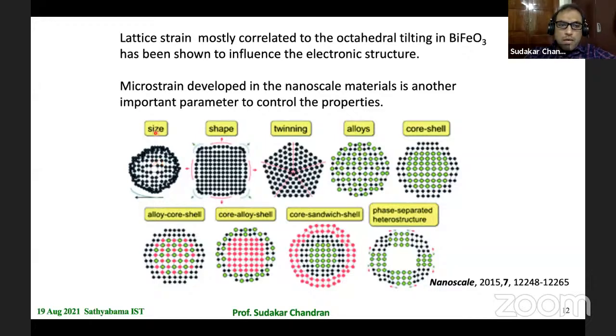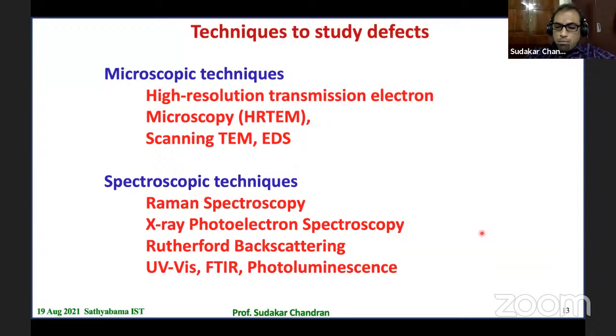And this microstrain can come because of the size or shape effect, and it can also come because of the alloying, or what kind of core shell structure you have, and lots of other things can contribute to this kind of microstrain. And in fact, I'm going to show in the BiFeO3 example that the microstrain we estimated on BiFeO3 nanoparticles influences the optical properties a lot. So let me also emphasize that if you want to study the defect structures, you have to use a different set of tools to identify them.